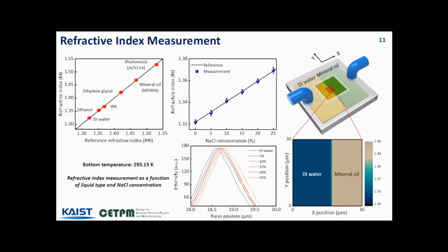We injected various liquids into the microchannel and measured their refractive indices. The measured refractive indices of these liquids differ by less than 0.4% from the values reported for liquids in the near-infrared range. This demonstrates that we can accurately measure the refractive index of the injected liquid.